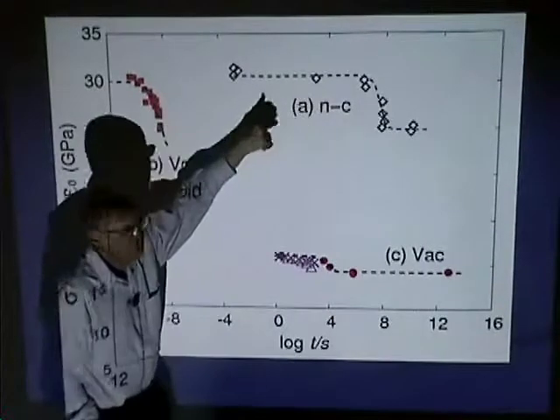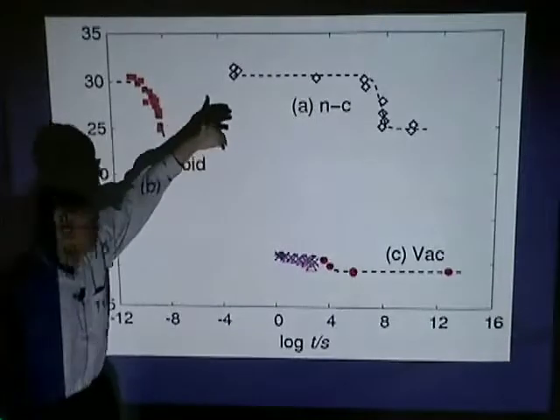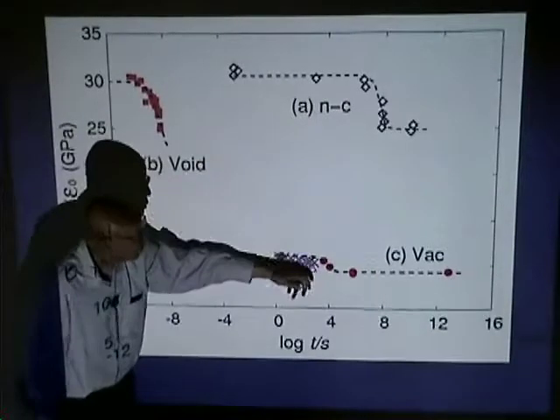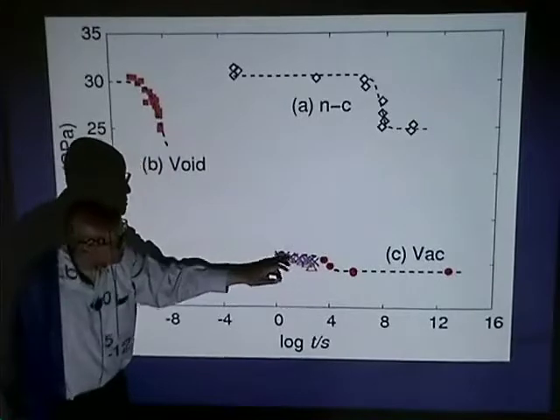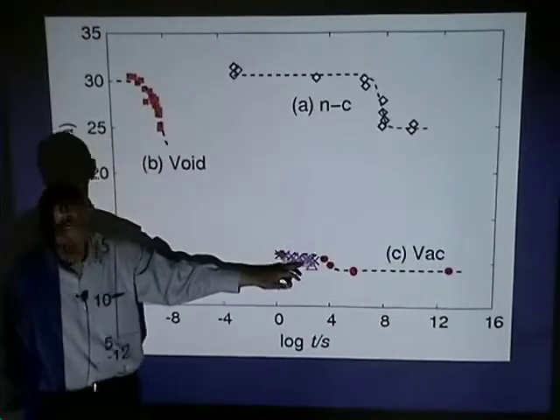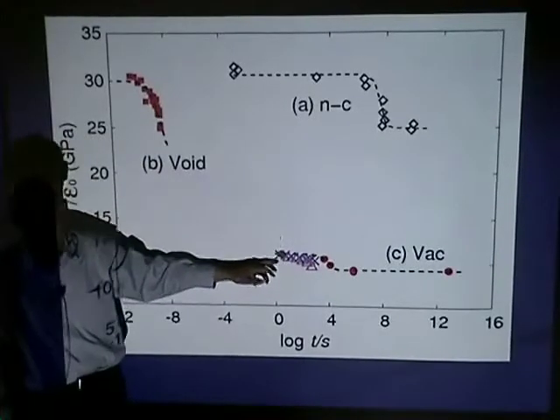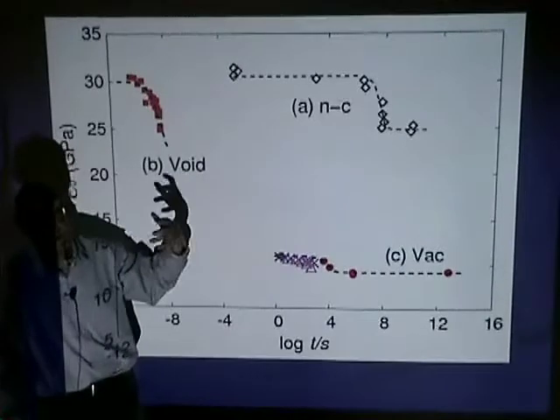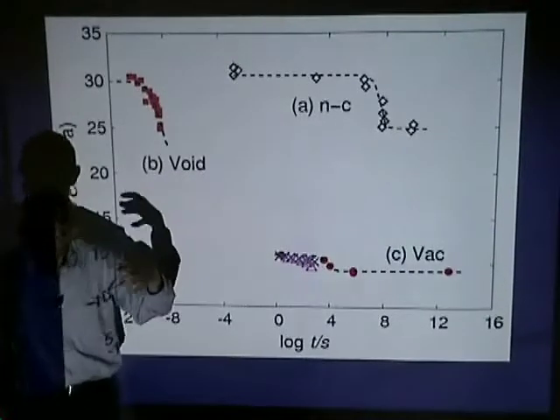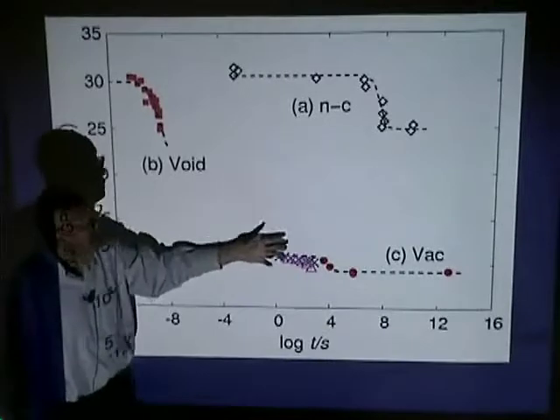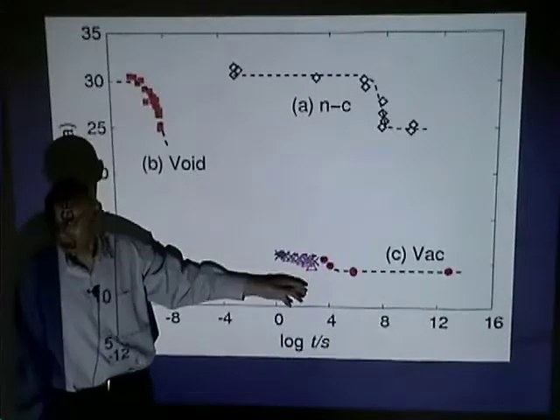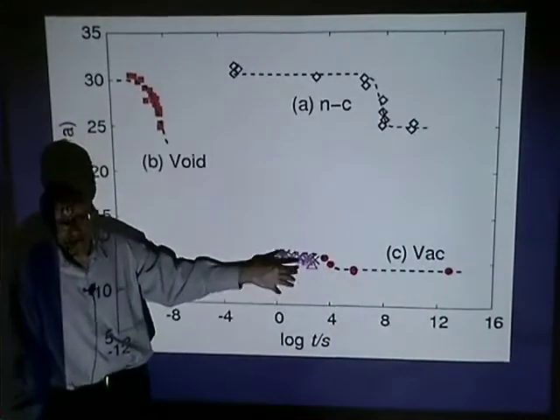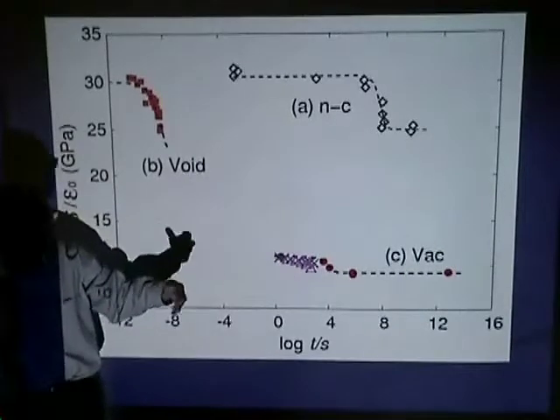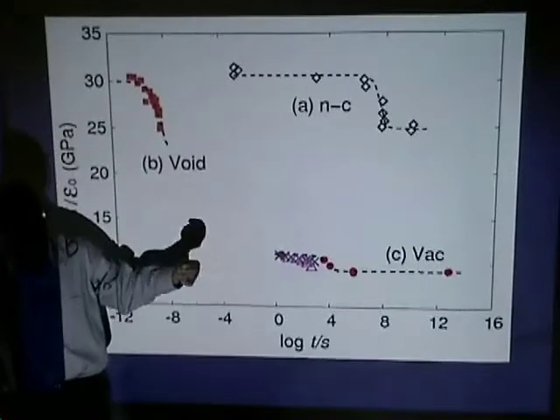As soon as we introduce some vacancies, the relaxation time drops by 3 orders of magnitude. So now the simulation is almost very close to the experiment. So this gives us now a control on, this gives an understanding of what controls the relaxation time that you measure. Okay, so in some sense, this is another way of understanding relaxation phenomenon.